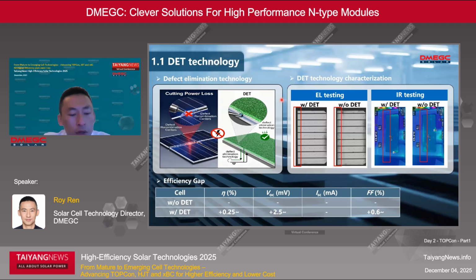Now I will give a detailed introduction to defect elimination technology. We know that a large number of defects will be introduced during the half-cut process of the cell. This technology will eliminate the defects. From the defect elimination calculation, we can observe that the yield with and without it will differ, with a color difference under the EL and an efficiency gap. We can achieve a conversion efficiency improvement of nearly 0.25%, especially in VOC and fill factor.